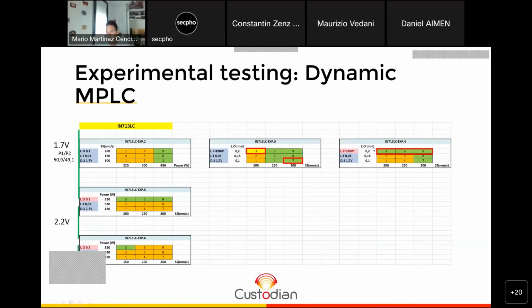We selected some of the most promising shapes regarding the Inconel 713. CM247 is being characterized right now, but what we can see here is the sample 3/3 on the left presents evident cracks, especially on the bottom and on the top part, while a fairly sound structure is observed at the mid thickness. Cracks show features of intergranular hot tears, which are already observed in alloys produced by standard powder bed fusion systems. And on the other hand, sample 3/7 was selected just for the sake of comparison, because, as you can see, it presents a huge amount of cracks and lack of fusion.